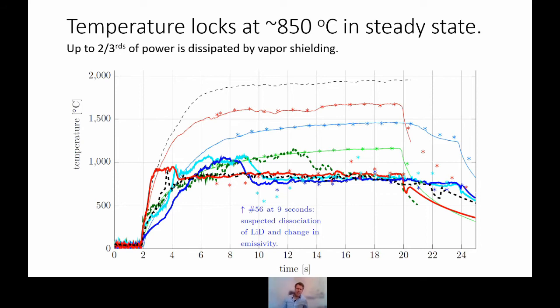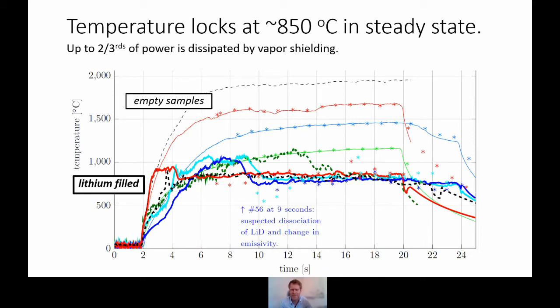Now, the temperature is maybe the most trivial thing, but I find it also the most interesting and most insightful thing. So what we see here is a striking difference if we view the temperature over time between samples that have been put in as a reference, so a 3D printed sample without any liquid metal inside, and on the other hand, samples filled with lithium. And the striking thing is that, of course, for the empty samples, if you increase the power gradually until 16 megawatt per square meter, which is very significant, the temperature of the samples increases. While for the lithium, this doesn't seem to be the case. The temperature is fixed. There is no change in temperature for some reason. And the reason is vapor shielding.